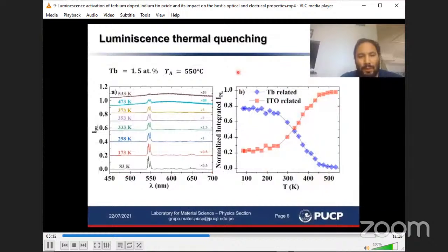In order to probe the potential excitation mechanisms between the host, or any transfer mechanism between the host and the terbium ions, we perform temperature-dependent photoluminescence measurements on a sample grown with 1.5 atomic percent terbium and annealed at 550 degrees Celsius. Here I'm showing you the emission intensity versus wavelength for different sample temperatures, and on the right, the integrated emission intensity associated with terbium and with the host.